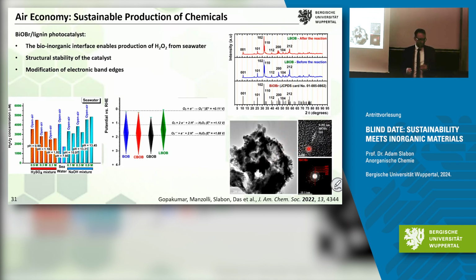And what's happening here, we found that we have a shift in the band edges actually. If you have the lignin with the photocatalyst, you have a higher conduction band edge than for the others. So my thought is that by modulation of the electronic structure in this case, which we see here from the Schottky measurement, you can most likely influence the reaction parameters. So you can see we can address materials sustainable goals by working hand in hand with nature.